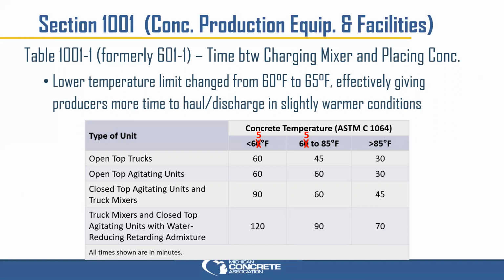Our rationale for this change, we suggested this as an industry and MDOT agreed, is that most mixes nowadays have a minimum supplementary cementitious content, fly ash or slag cement. Fly ash and slag cement make better performing concrete overall, long-term especially. We said that because of this, that has a retarding effect in most cases, particularly in the normal to cooler temperature ranges. So we said, what if we bump that lower temperature limit from 60 to 65? Therefore, in those still fairly cool but slightly warmer temperatures, we still get that longer haul time on our concrete.